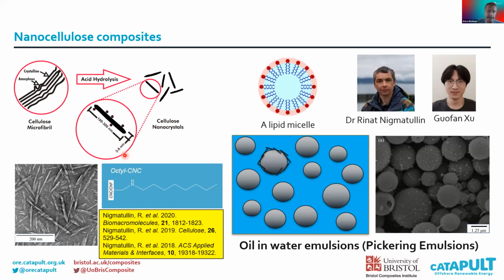Now, we've also been able to add some octyl groups. So this is a carbon chain on the surface. So this is a hydrophobic group. We've been able to do it where we also retain the charge. So what we end up with is effectively a surfactant-like material, a bit like soap. Now, we know soap forms what we call micelles in water, where these fatty chains, these hydrophobic groups, point towards the dirt. They encapsulate the dirt, and the charge points towards the water. So you can actually encapsulate dirt, and that's how soap works. It sort of washes the dirt off your hands.